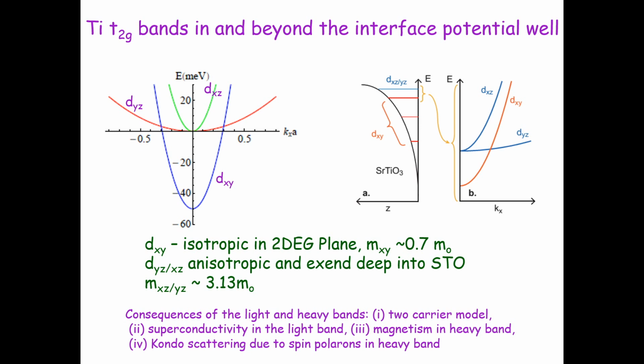So that makes the mobility larger. And so the final consequence of this is our summary. So we have a two carrier model. We think that superconductivity is in the light carrier band, the high mobility band, and the magnetism is coming from here. And if at all there is magnetism, in our case the only evidence of magnetism is the Kondo scattering coming from these localized moments which are confined at dxy.